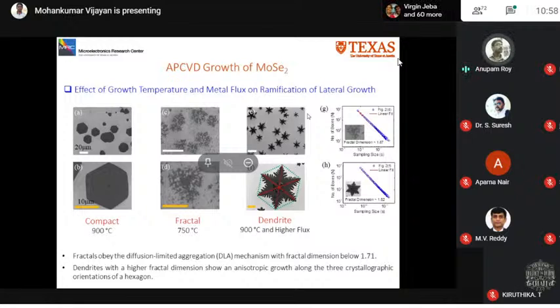So now, although the edge diffusion still takes place at elevated temperature, it may not be sufficient to ensure the rearrangement of all incoming adatoms to achieve a stable triangular or hexagonal configuration, and hence the compact structure will ramify. And you can see that the needle-like central branches indicate the preferred growth directions. So higher metal flux increases the number of preferred growth directions, and the high temperature regime promotes the anisotropy of the edge diffusion. The adatoms, in addition to the attachment to the edges, now also prefer to diffuse along the lowest energy diffusion paths on the substrate, promoting the branching and leading to dendritic domains.